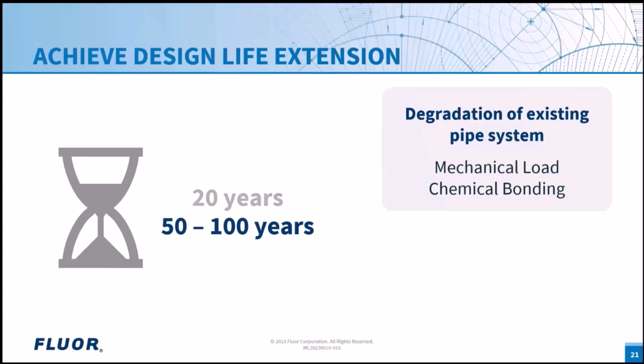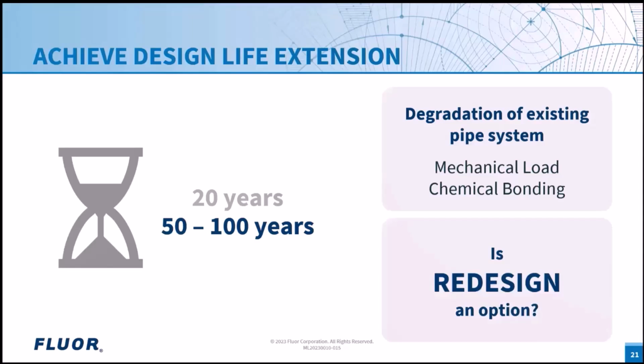From a performance-based perspective, at the end of the initial material design life, it is difficult to assess what the progress of these mechanisms during the plant's life has been, and what the remaining life in the material is. Is redesign an option? Well, this would mean we need to go back to square one and redesign for a design life of 50 years instead of 20 years. This would only make sense if we have reliable records of 20 years of loading, mainly pressure and temperature, if these are available. Furthermore, full material regression reports shall be available that allow for determination of a 50 years failure stress level, and in particular for the diffusion related issues like water ingress.